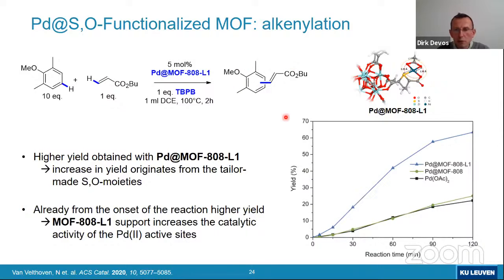And I'm not going to discuss all the catalytic optimizations that we did for this reaction, or that Niels did for this reaction, but maybe the most telling about the effect of the MOF, in this case the ligand L1-modified MOF, so the MOF modified with this thioether ligand, is what you see here in the initial kinetics. If you compare the homogeneous reaction with palladium acetate with the reaction with just palladium on the MOF-808, so without the thioether, and if you see then what happens with the thioether ligand, then it's obvious, of course, that the initial rate from the onset of the reaction is just higher if you modify the MOF with this thioether carboxylic acid group.